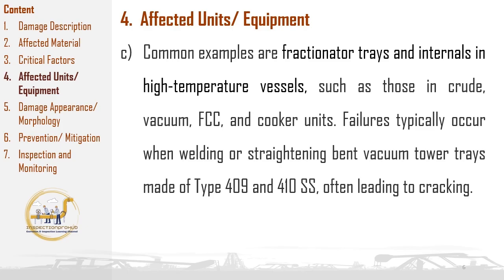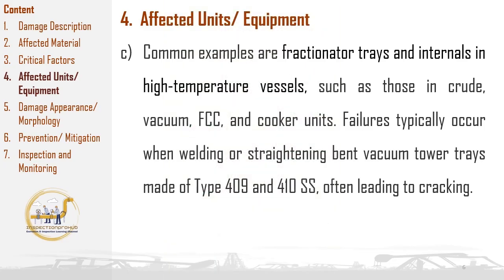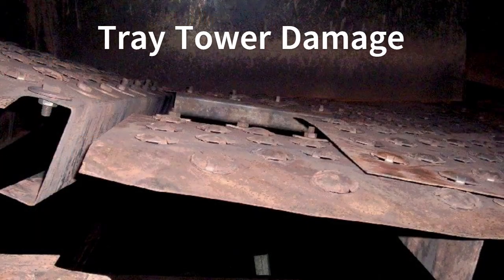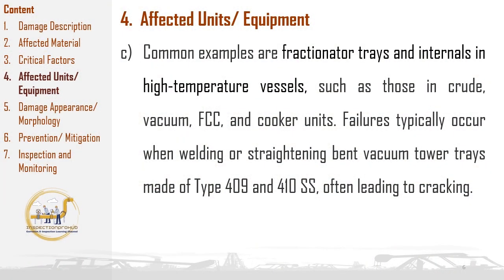Affected units and equipment commonly include fractionator trays and internals in high-temperature vessels, particularly within crude, vacuum, fluid catalytic cracking, and coker units. These components are often exposed to temperatures that can lead to embrittlement, especially when made from ferritic stainless steels like Type 409 and 410. Failures are frequently observed during maintenance activities such as welding or straightening of vacuum tower trays, as the heat exposure in these processes can induce or worsen brittle phases in the material, making it more susceptible to cracking. Proper handling and careful control of welding practices are essential to minimize this risk and maintain equipment integrity in high-temperature environments.